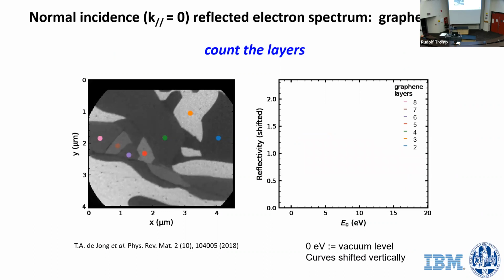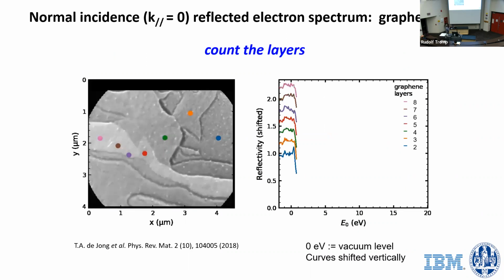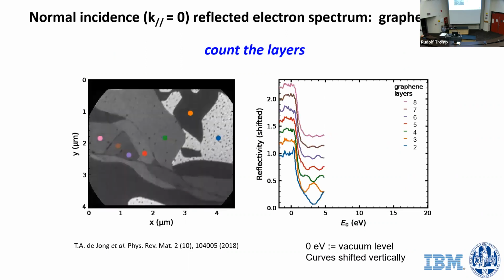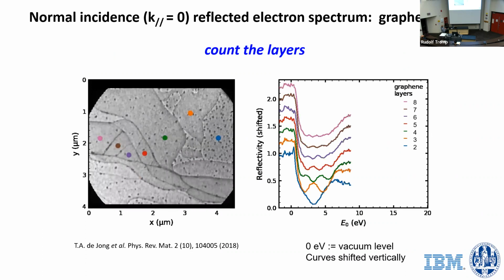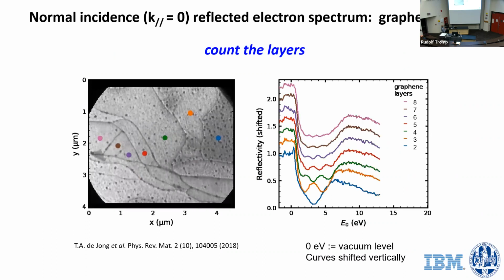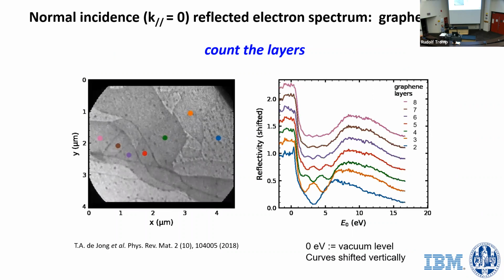And I'm going to show you again a graphene sample. This is graphene on silicon carbide. And we're at normal incidence, and we're going to measure the reflectivity on different places. You see the different places have different colors. And you see that we get different reflectivities, right?